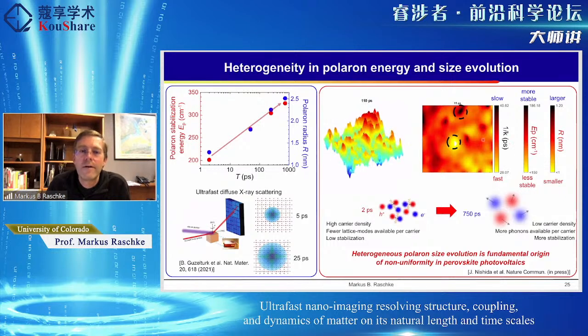And so if you look at, for example, a time slice here at some particular time, then you actually see that there are locally regions where polarons are more stable and larger. And so this would actually be a desirable effect, because then you expect that these polarons have more time or are less susceptible to defect scattering and can give rise to photocurrent, whereas there are locally regions which are less stable with smaller polarons, and this may be a less desirable thing.